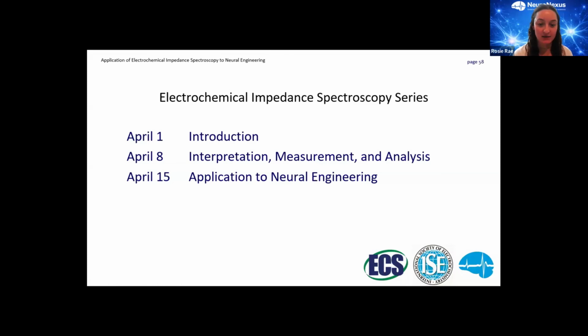One person asks, when we collect EIS over the course of a corrosion experiment, we typically fit the same equivalent circuit to every time point, but the interface is physically changing, for example, during active pitting and passivation. Is it justified to use a single circuit model for fitting all of those stages? And are there established frameworks for deriving a time-dependent impedance model directly from the underlying kinetics and transport equations? Wow, that is a long question.